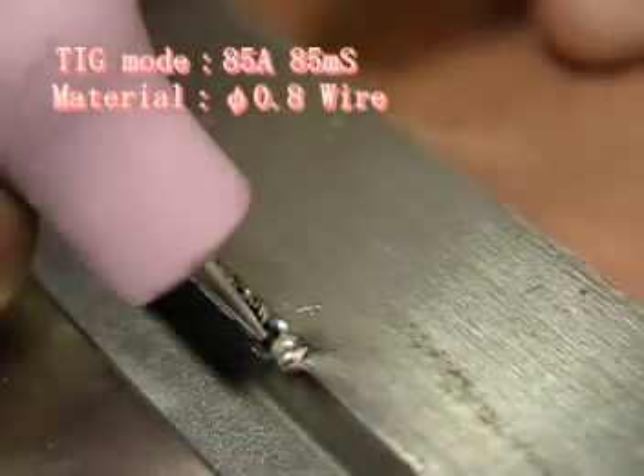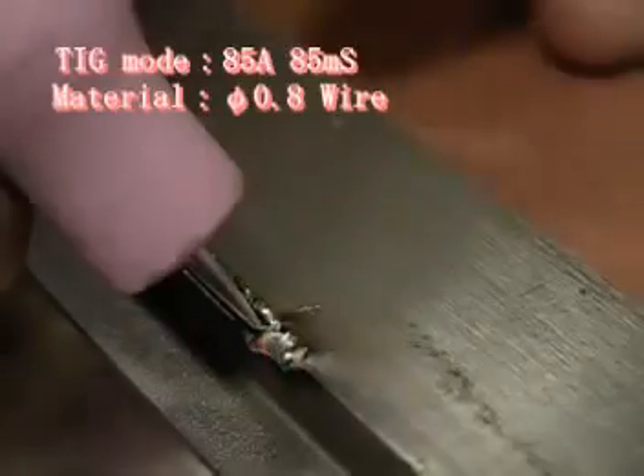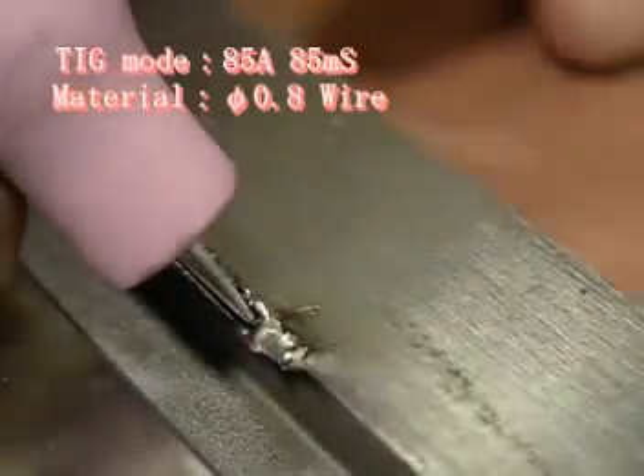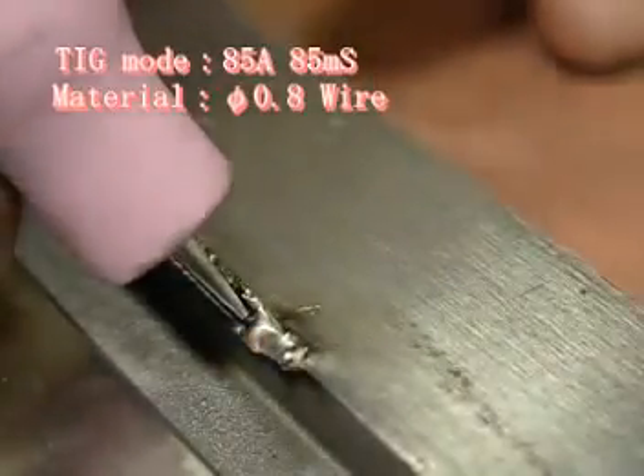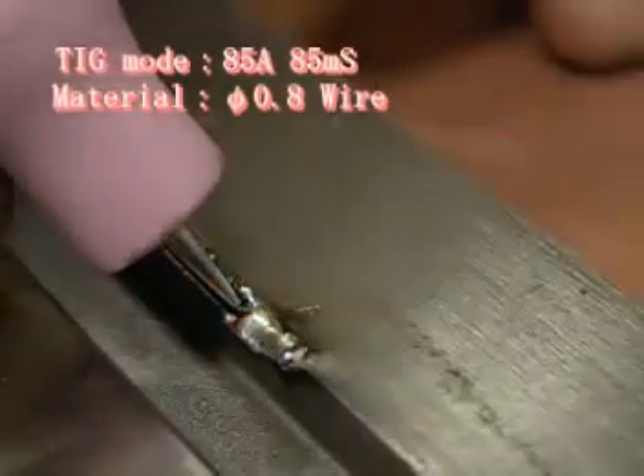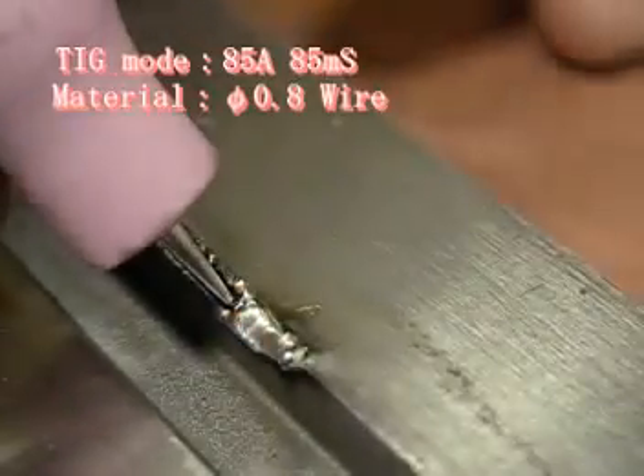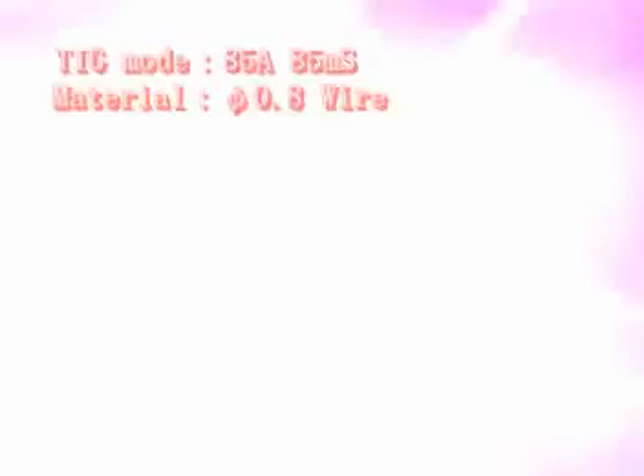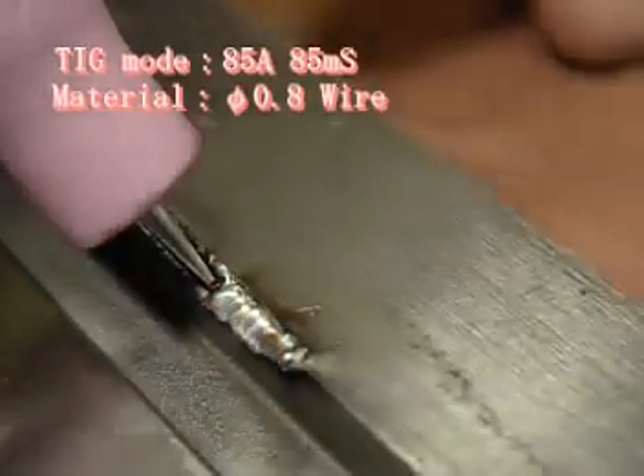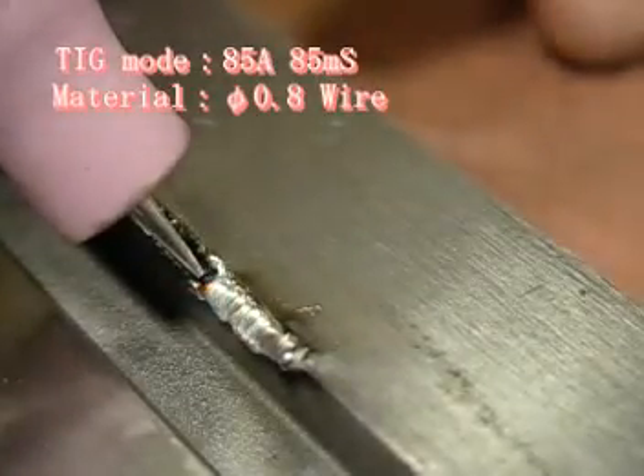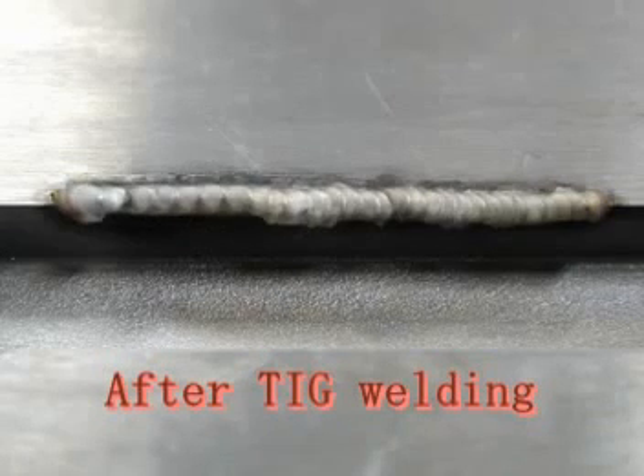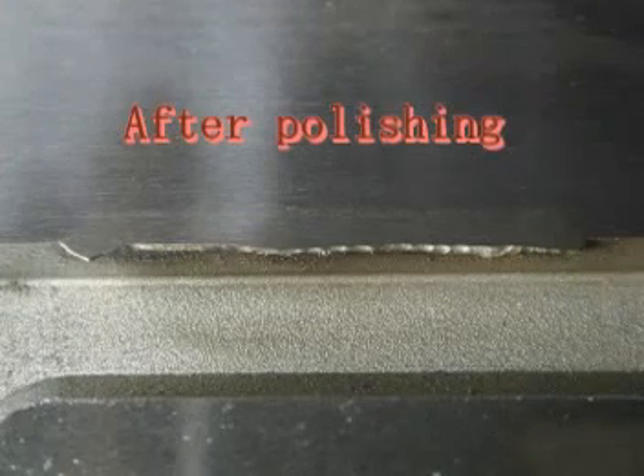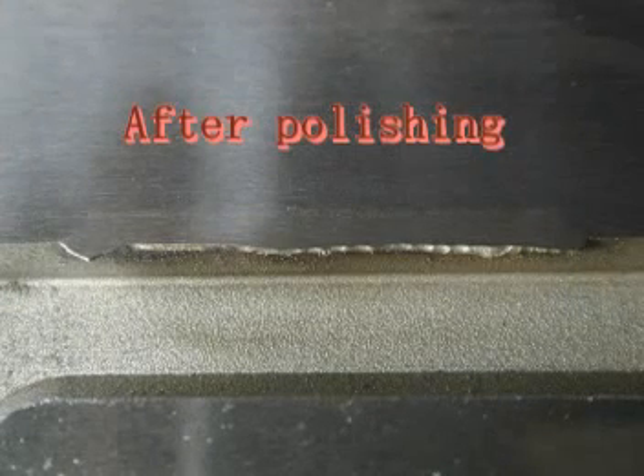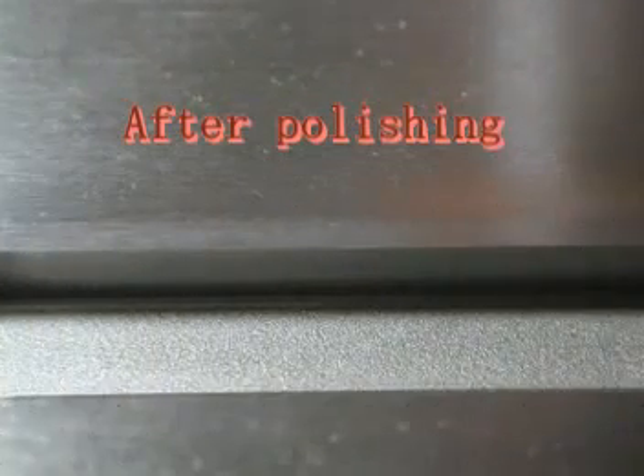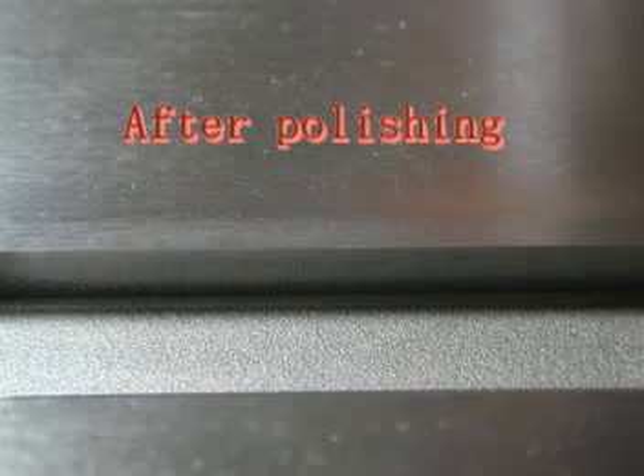After melting down both ends, melt the middle part of the material. In this operation, move the electrode slowly to overlap the weld bead slightly. Avoid moving the electrode too much, which results in an uneven welding surface. In this way, you will have a perfect welding surface without irregularities. You can confirm that there is no shrinkage or parting lines after grinding the welding surface.